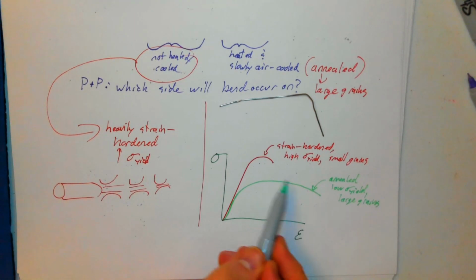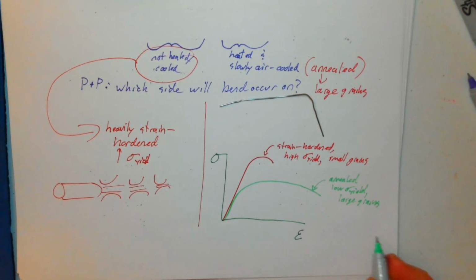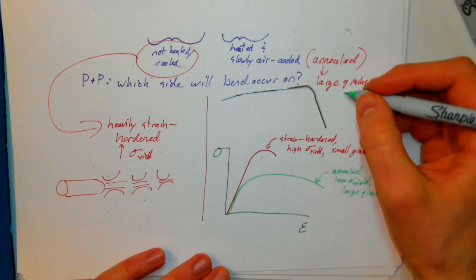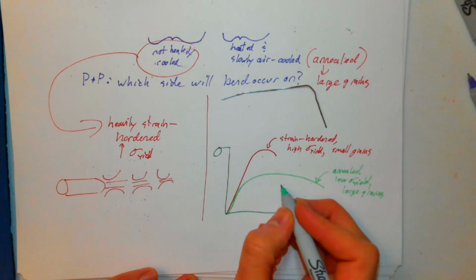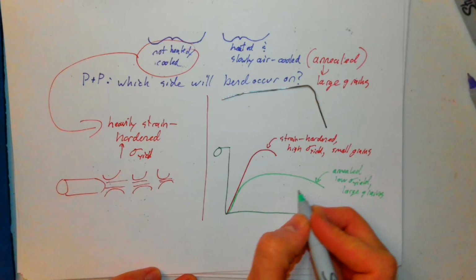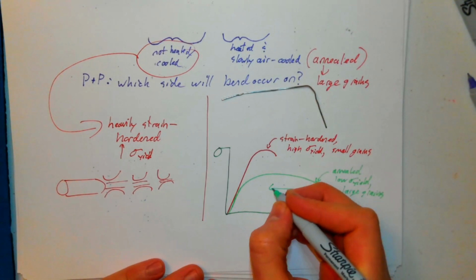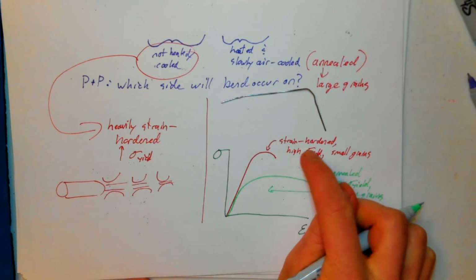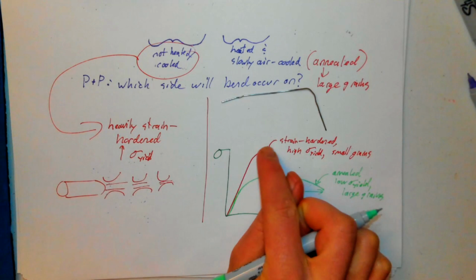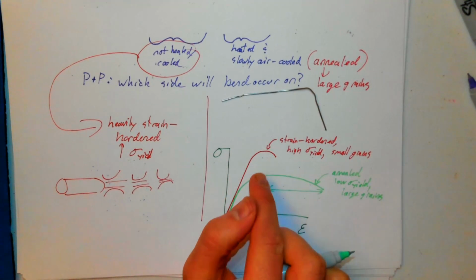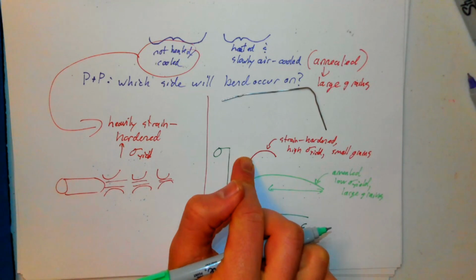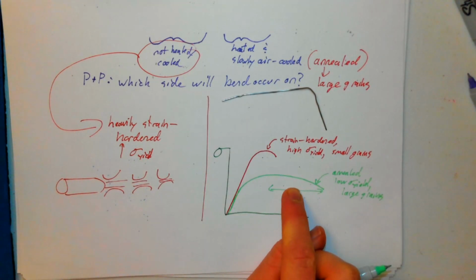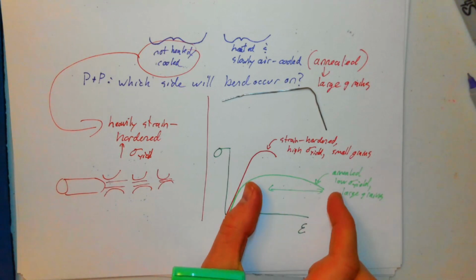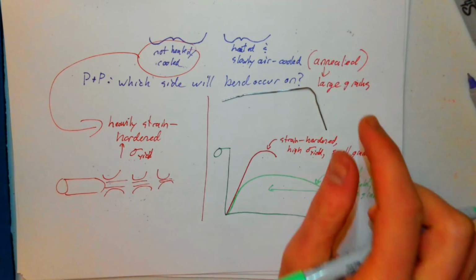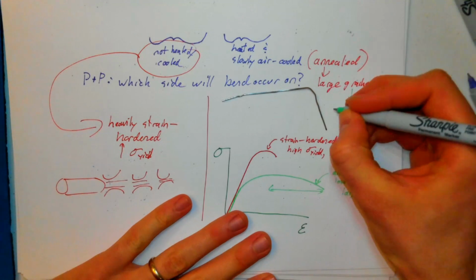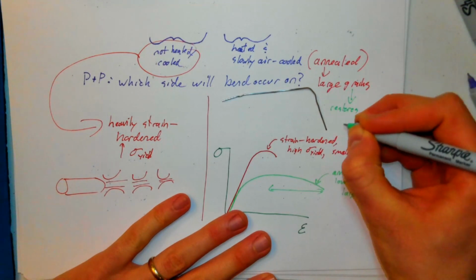But one key feature that we're looking at here is that the annealing process gives us large grains, but it actually restores the ductility. Right? So remember from a previous lecture, when you strain harden a material, you typically decrease its ductility but increase its yield strength. You can restore a material back to a lower yield strength and more ductility by annealing it. So it gives us large grains, but it also restores ductility.